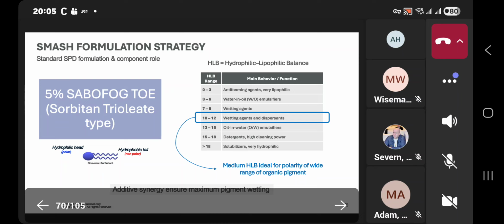The scale is defined from 0 to 20, as you can see on the table, and the Sabofog has a value of about 11. So this is right of the middle of the scale. This means the balance is almost 50-50 between the polar and the non-polar part of the surfactant, and this is ideal for the polarity of a wide range of organic pigments. We also tested other surfactants with other HLB values, but it did not show any dispersion improvement in our process.